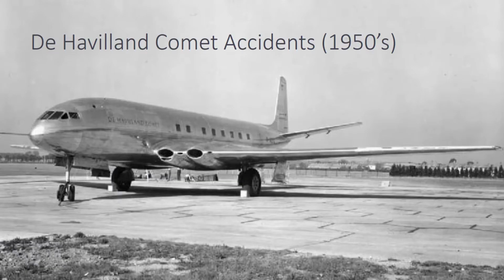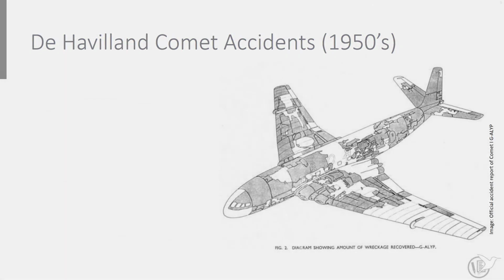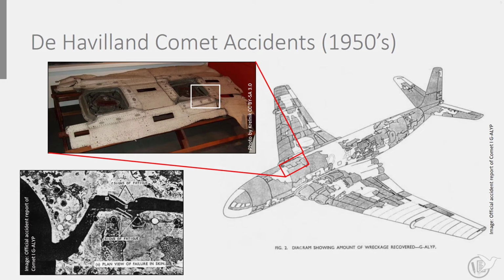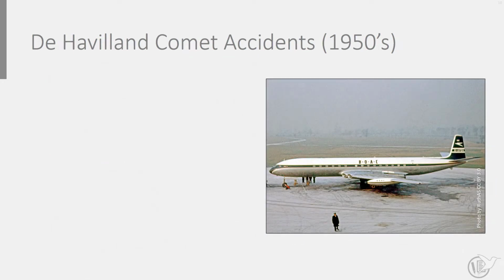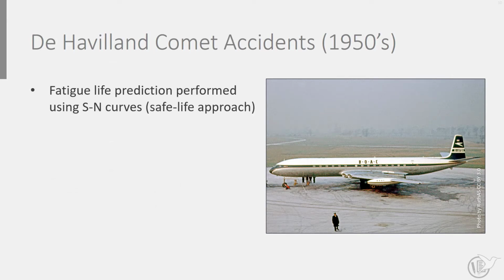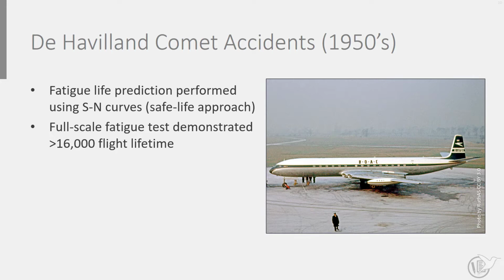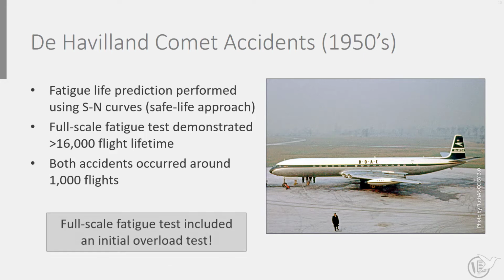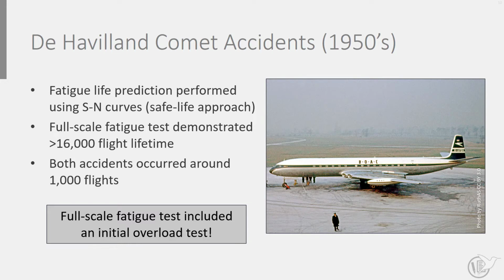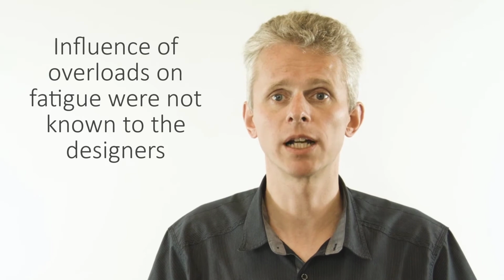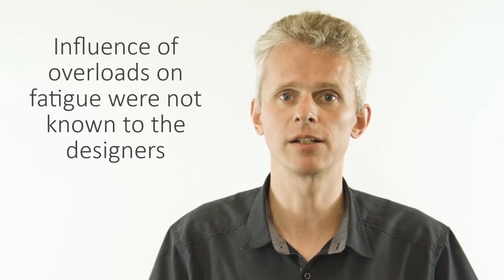Well-known aircraft accidents associated with the safe life design principle are the de Havilland Comet accidents in the 50s of last century. With two of these aircraft, the fuselage exploded during cruise at high altitude. Cracking occurred at window cutouts imposed by the rather high stresses. These accidents were not expected because fatigue was considered in the design. For example, the full-scale fatigue test resulted in failure after about 16,000 flights, while both aircraft accidents occurred near 1,000 flights. This difference is attributed to the fact that the full-scale fatigue test was executed after the overload test was applied. This resulted in favorable stress redistributions, relieving fatigue-critical locations. Repeating the test with an aircraft taken from service resulted in only 3,000 flights until failure.